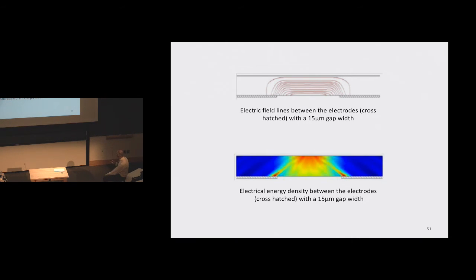This is potential LFE, AlN biosensing platform, which we think would be extremely interesting in terms of looking at very, very low concentration analytes that might be present, for example, in biomarkers associated with cancer and things of that nature. Further, this is a COMSOL calculation of the electric field between the electrodes, 15 micron gap width. This is on aluminum nitride, and you see the electric field here is primarily in the direction horizontal, which is what it should be. And here is the electrical density between the electrodes, and red being the highest density, indicating in terms of the energy.